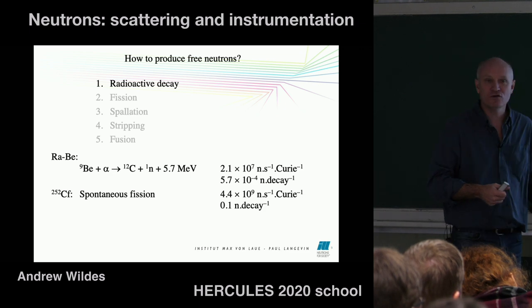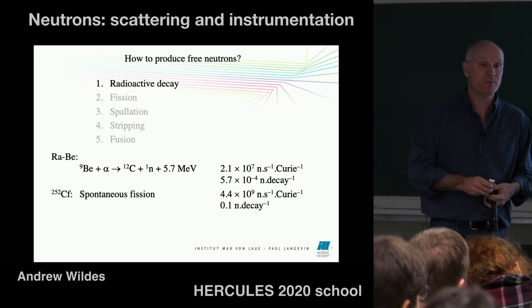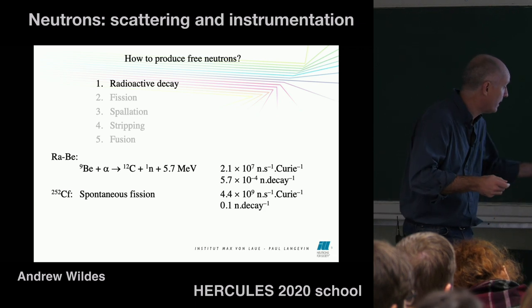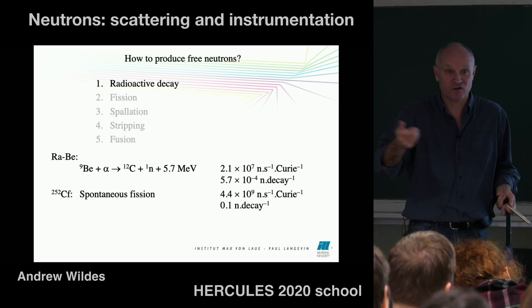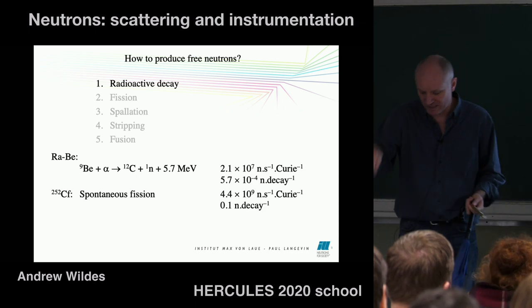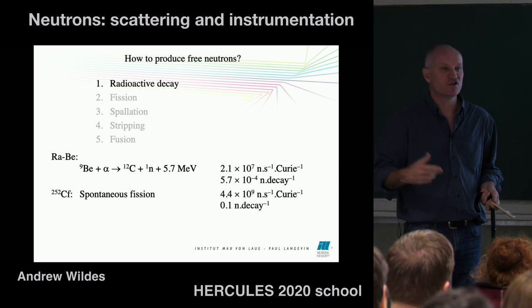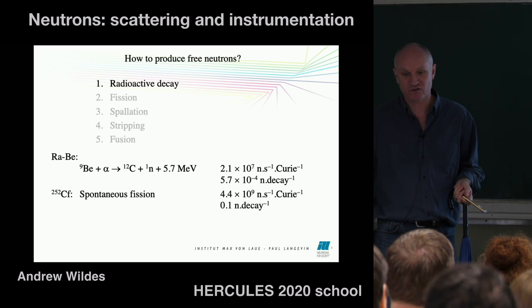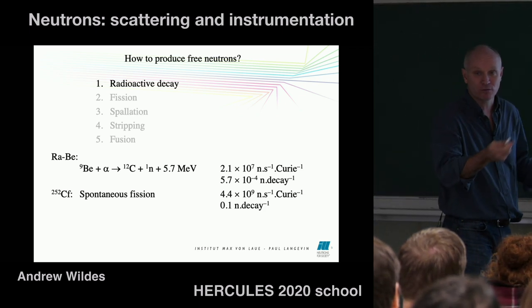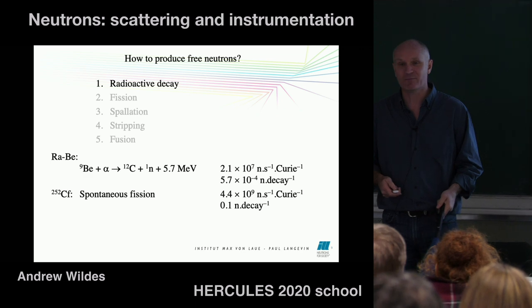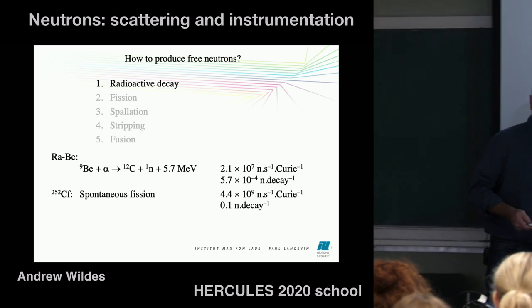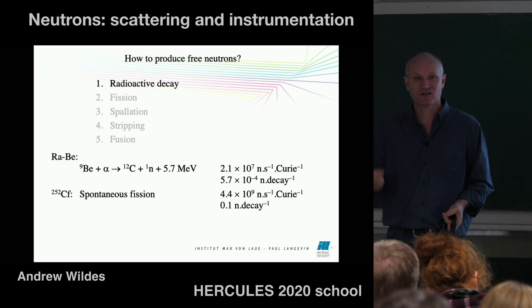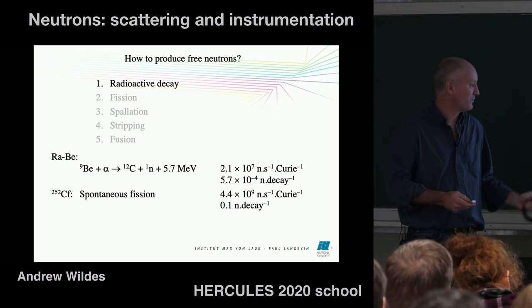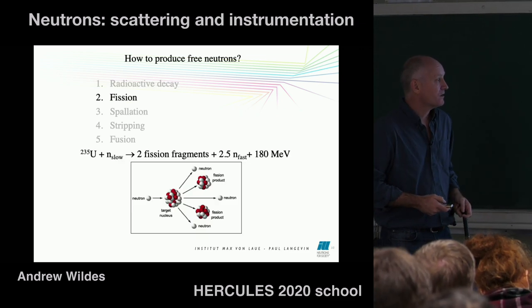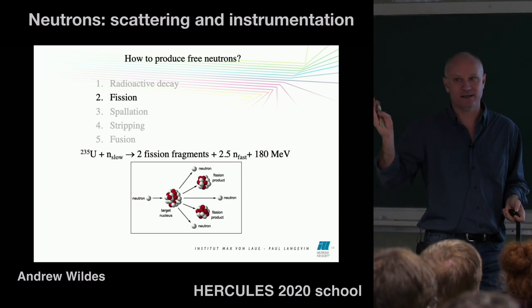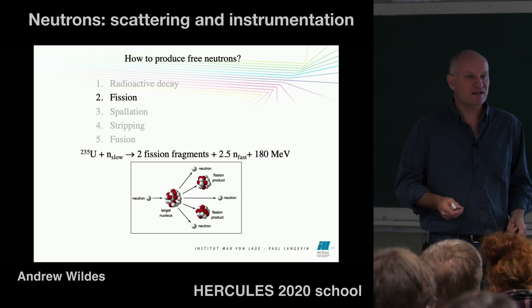And in fact, they use this for things like humidity detectors, all right? So you can buy things like humidity detectors for, say, the soil, which will contain this. You stick it into the soil, and it produces neutrons. You detect the neutrons, you're able to work out what the humidity of your soil is. That's actually a commercially available material. But it's not really used for neutron scattering because it's still quite inefficient. You're not producing very many neutrons, and it's quite difficult to get large quantities of this californium isotope.